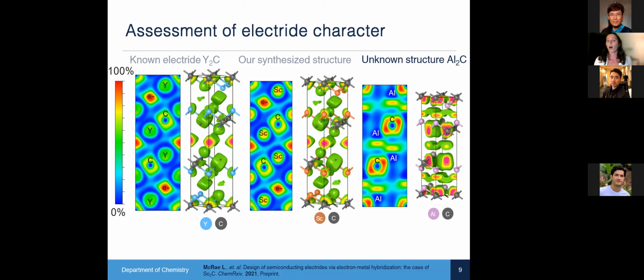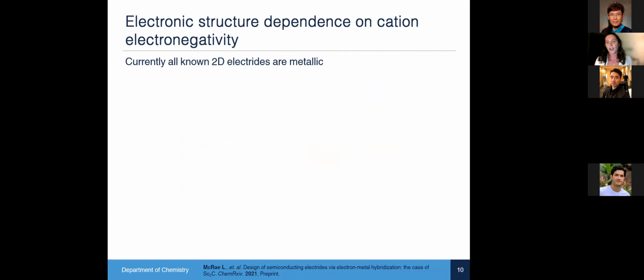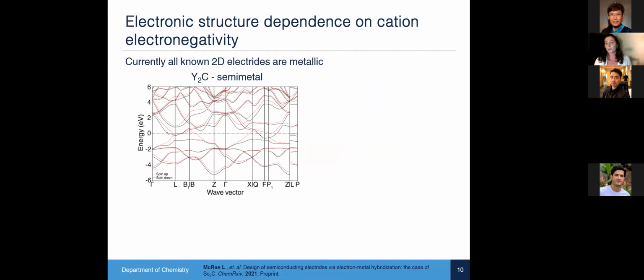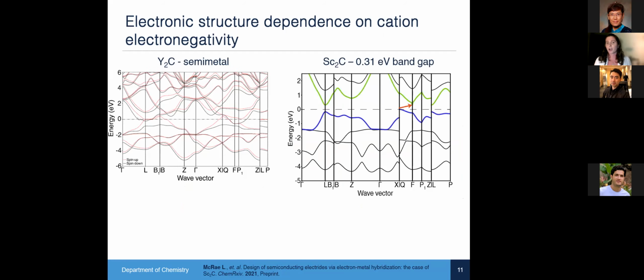We wanted to understand how all of this plays a role in electronic structure, because currently all known 2D electrides are metallic. So the yttrium carbide is the only example of a semi-metal that exists in these 2D electrides. So we calculated the band structure for scandium carbide and found that, in fact, the bands do start to split now that we have a more electronegative cation incorporated. So we see a very small band gap in the scandium carbide structure. We measured the conductivity experimentally to see if our experimental structure is also semiconducting.